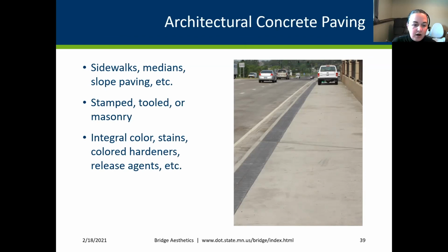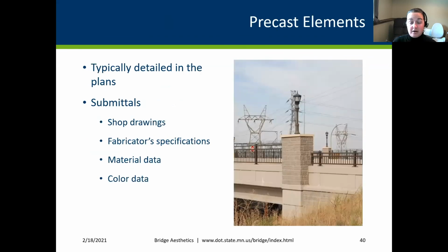We're also doing more stains and color hardeners and colored release agents instead of integral colored concretes. We've noticed that integral colored concrete just isn't holding up as well. Its lifespan is not as long. So financially and longevity-wise, we're trying to avoid integral colored concretes. Outside of maybe our precast elements, the only thing we do in precast are custom emblems, like sometimes a city name or something like that, and then these precast caps. That's about all that we're going to do in a precast type of situation.